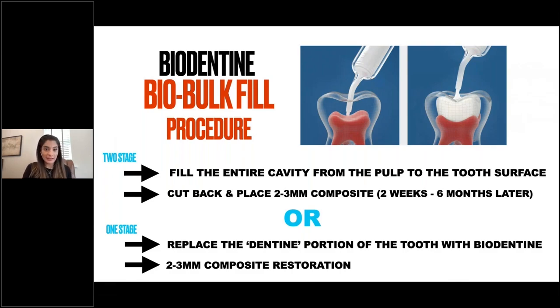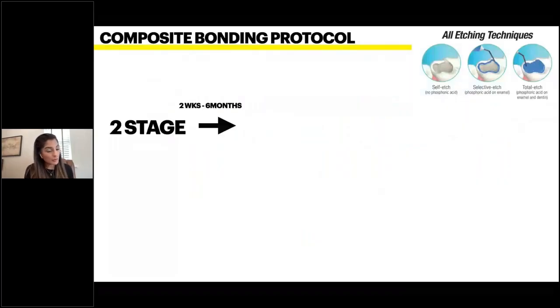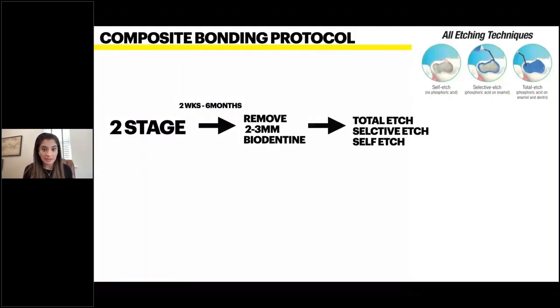Now, if you're doing it in these ways, we need to know how to restore the tooth with composite afterwards. So what is our composite bonding protocol? So if you're doing it in 2 stages, you've left the Biodentine for a while, like we talked about, and you've come back. At that point, you're removing your Biodentine, and you can do any etching procedure you want now over that Biodentine. So you can etch it, or you can choose selective etch or a self-etching procedure, and then you bond the composite on straight after that.